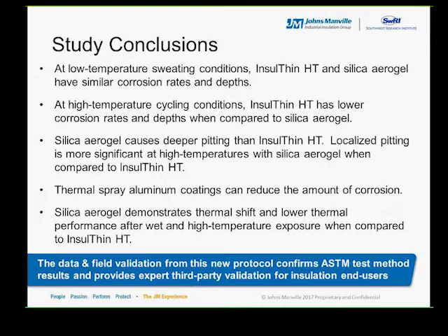Third, our analysis of a TSA coating showed it can reduce the amount of corrosion, and that this NACE test method that we just reviewed can be used not only for looking at insulation materials but also coatings. Fourth, based on some add-on testing that we did to complete the understanding of the thermal performance of the two different insulations after the corrosion, with accelerated corrosion conditions, we confirmed the presence of a thermal shift with the silica aerogel blanket, but not the InsulThin, at the wet and high temperature exposures.